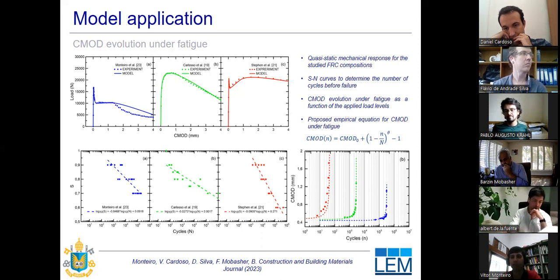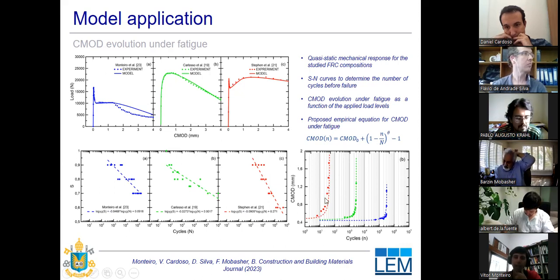So here we propose an empirical equation, which is here, and uses the initial CMOD, the cycle index, and an exponent that is based on the load level, and also make a fit on the experimental results we have from the lab.